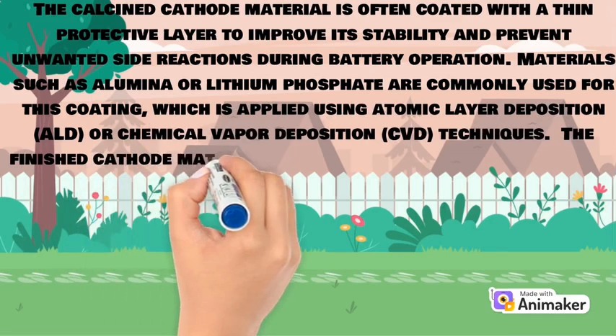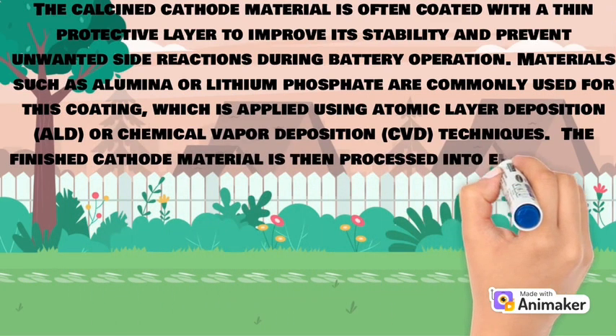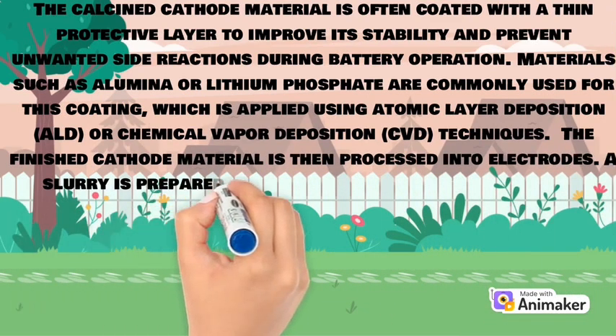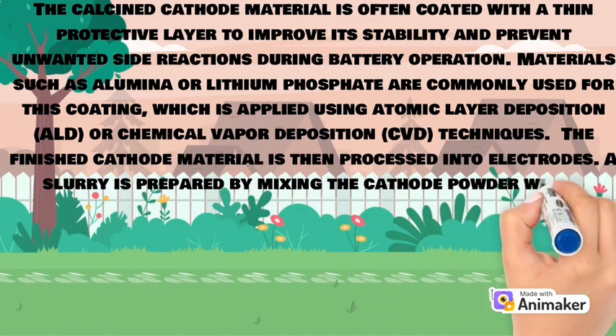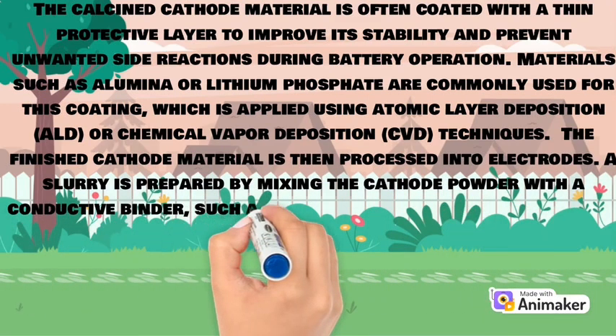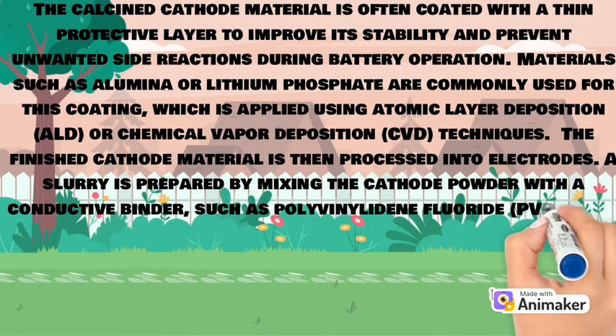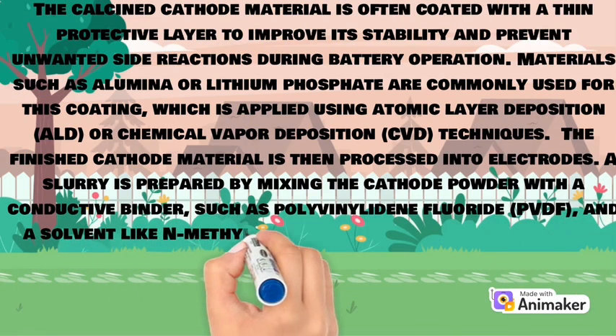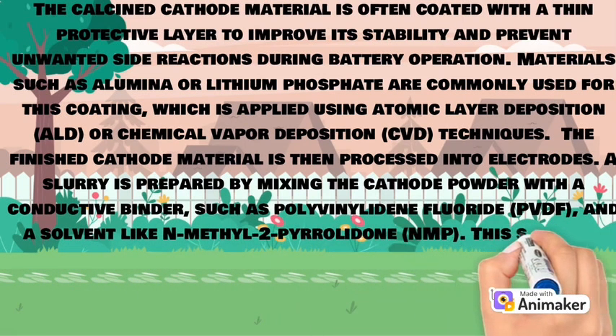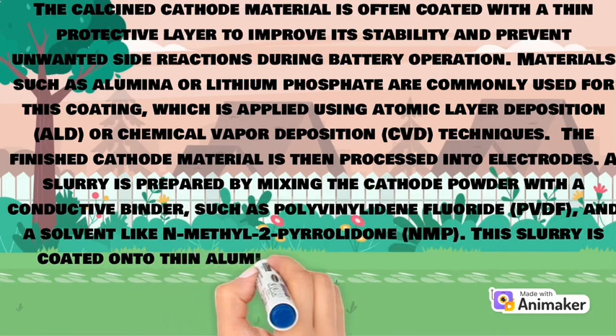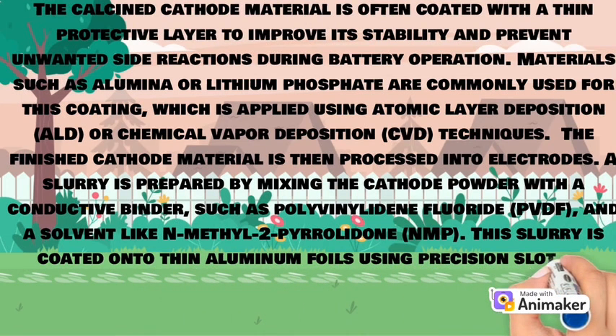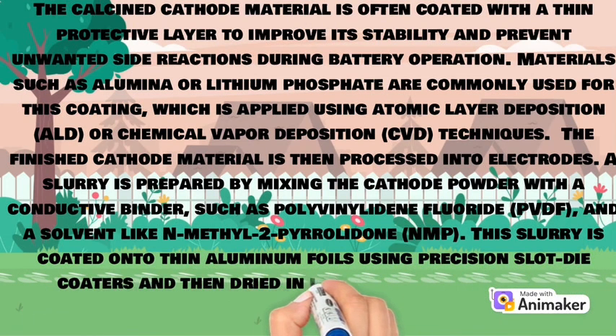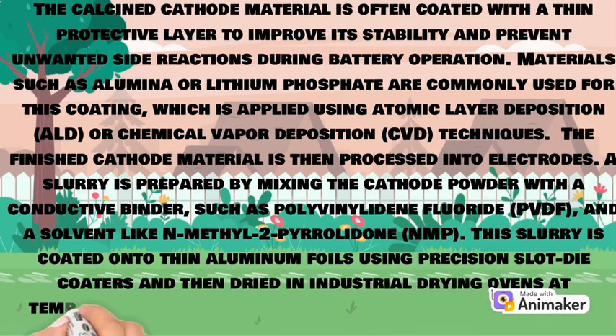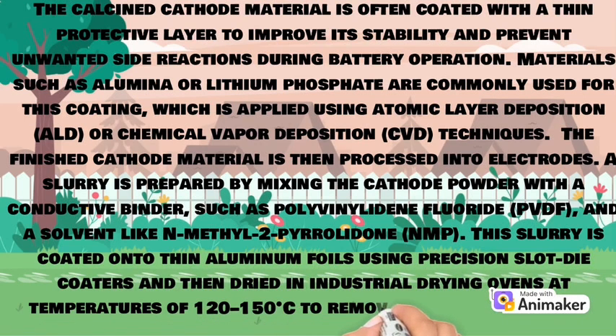The finished cathode material is then processed into electrodes. A slurry is prepared by mixing the cathode powder with a conductive binder such as polyvinylidene fluoride (PVDF) and a solvent like N-methylpyrrolidone. This slurry is coated onto thin aluminum foils using precision slot die coaters and then dried in industrial drying ovens at temperatures of 120 to 150 degrees Celsius to remove the solvent, leaving behind a uniform